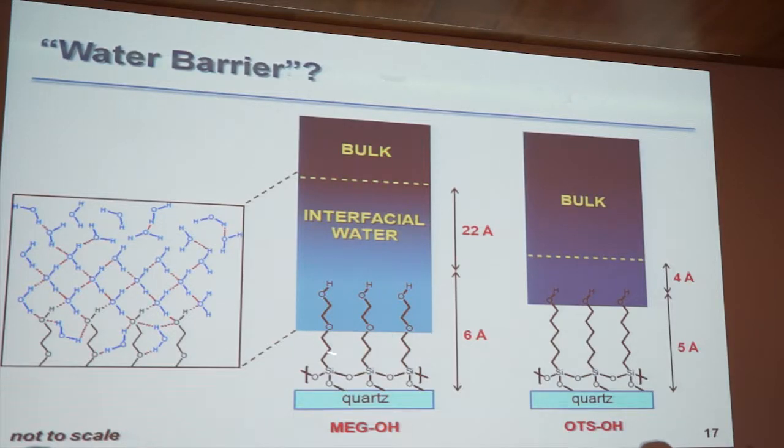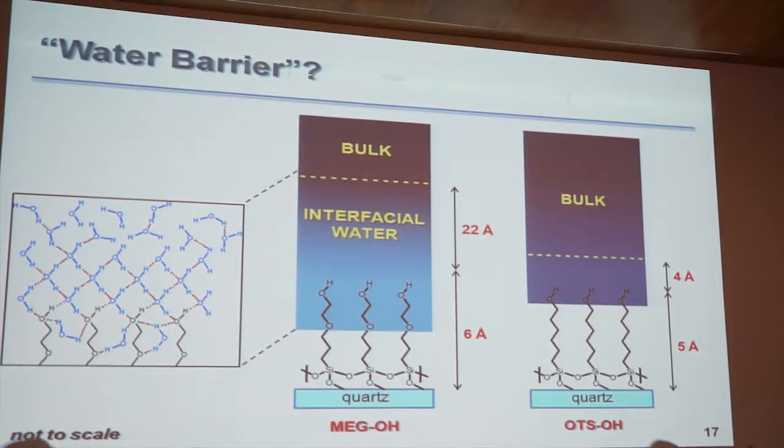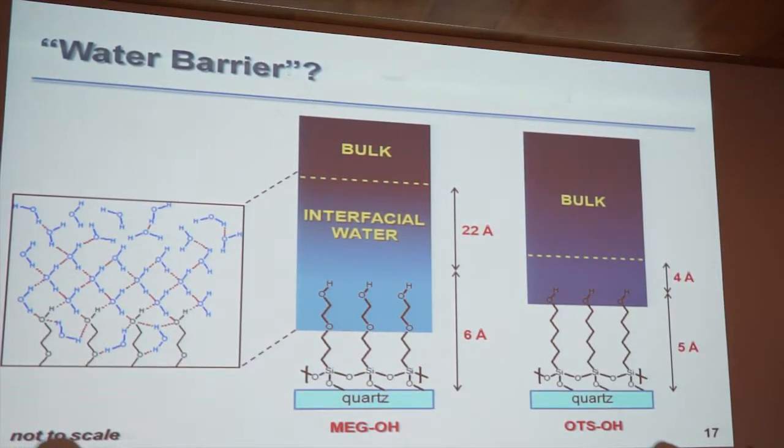It's a structured water. What the precise nature of that structured water is, we are not sure, but one thing is for sure: neutron reflectometry is actually seeing that. And also, as you move out into the liquid here, there's another different type of water, and then we find ourselves in the bulk. So to cut a long story short, this particular configuration is conferring remarkable biocompatible properties on whatever material.